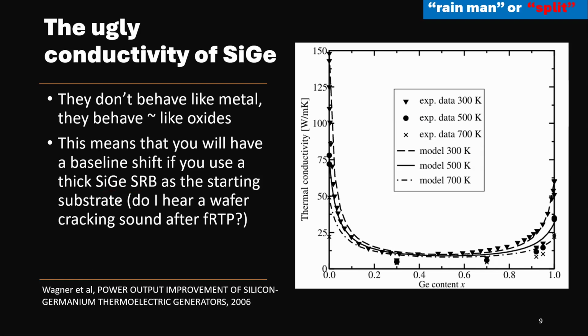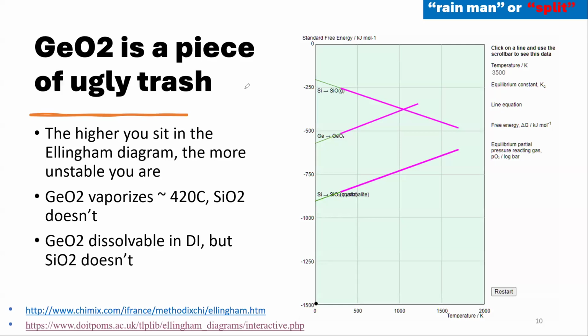But with that thick layer, what happened? Then the thermal conductivity behavior of the wafer will be in deep trouble. For example, if you send the wafer through this fast RTP process, very high temperature in 1 second, boom, 1000 degrees, and it comes down. Such a high thermal stress, your wafer with such a thick, close to oxide, low thermal conductivity material, you will hear a cracking sound. Your wafer could potentially break if this process is too fast, too high temperature, thermal stress too large, right? So I think we agree this is a split. It's hurting SiGe, all right? That's one. The other one is that germanium oxide is a piece of ugly trash.